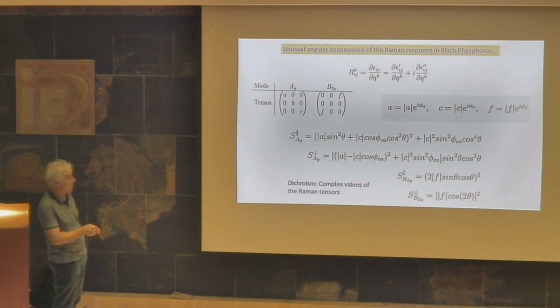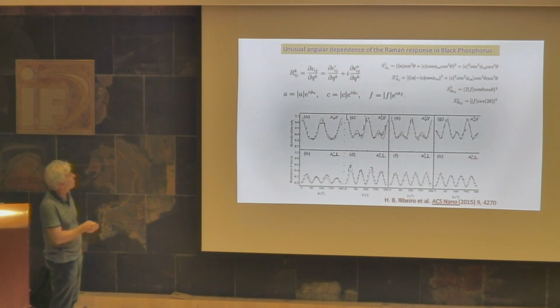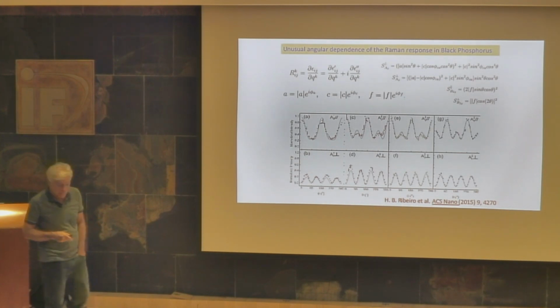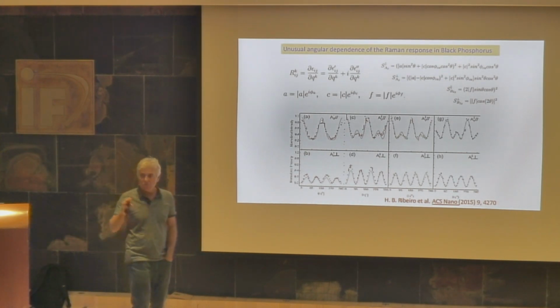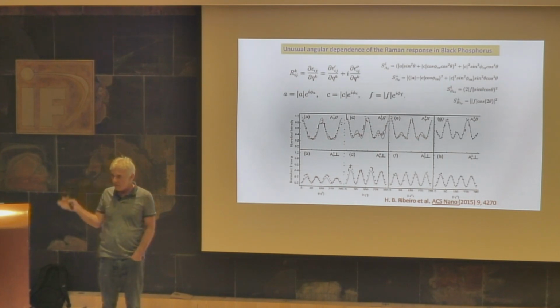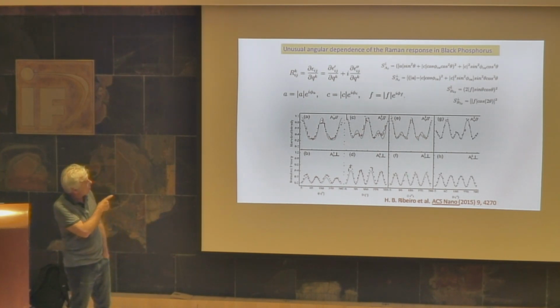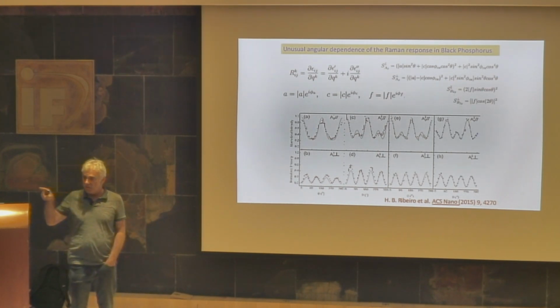Then we have this expression. Then we need to fit the data. For example, we could fit the data for the black phosphorus, and from the fitting we get the value of the Raman tensor elements. Then the Raman tensor depends on the symmetry. Each symmetry has a Raman tensor. The group of black phosphorus is the orthorhombic group.